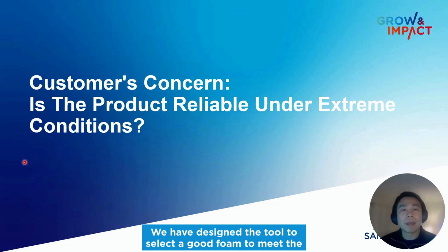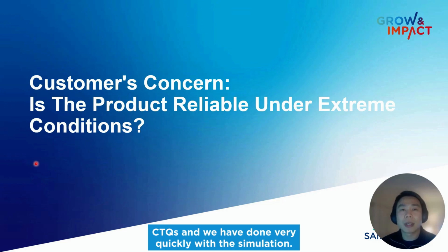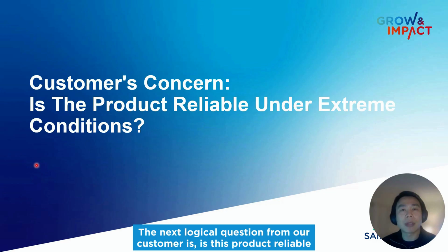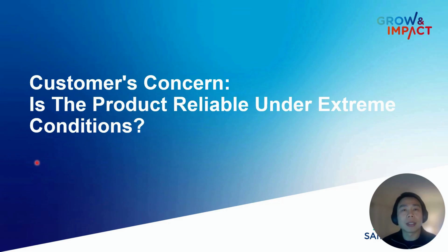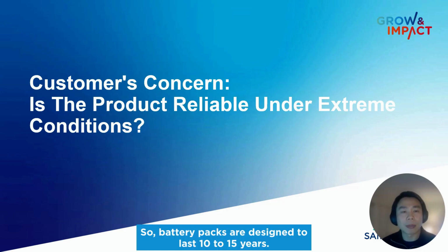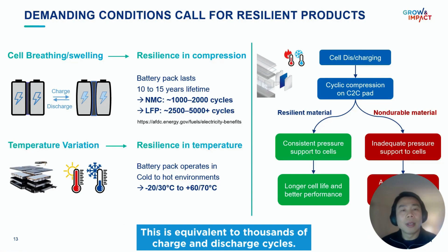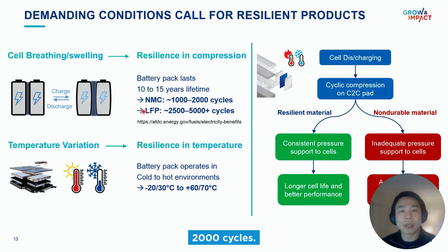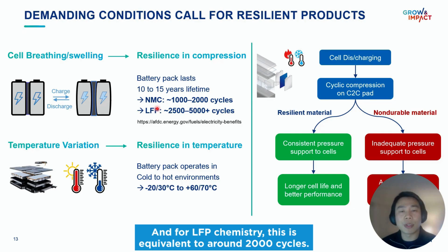So we have designed the tool to select a good foam to meet the CTQs, and we have done this very quickly with the simulation. The next logical question from our customer is, is this product reliable under extreme conditions? Battery packs are designed to last 10 to 15 years. This is equivalent to thousands of charge and discharge cycles. For example, for NMC chemistry cells, this is equivalent to 1,000 to 2,000 cycles, and for LFP chemistry, this is equivalent to around 2,500 to 5,000 cycles.